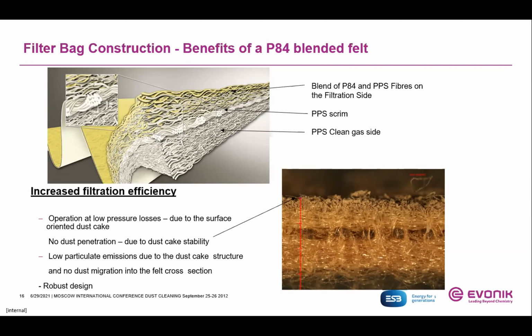If we are talking about scrubbing systems, then it's not just the material. Depending on the system, the reaction mustn't be entirely done in the reactor. There are systems where a significant portion of the desulfurization reaction takes place in the filter cake. The more you have this dust cake formed on the surface, the lower is the residual pressure drop of this construction. Therefore, the additional pressure drop that is accumulated during the filtration cycle helps to build a rich and porous cake, and actually helps to make the SO2 reaction and the SO2 reduction more efficient.